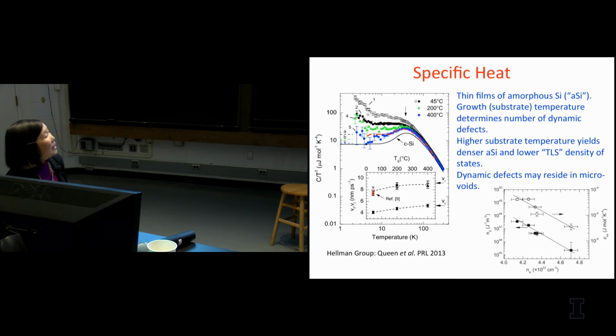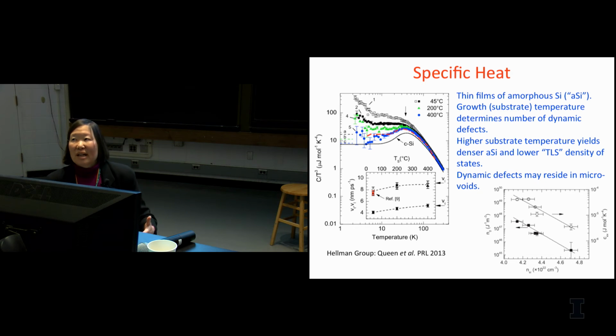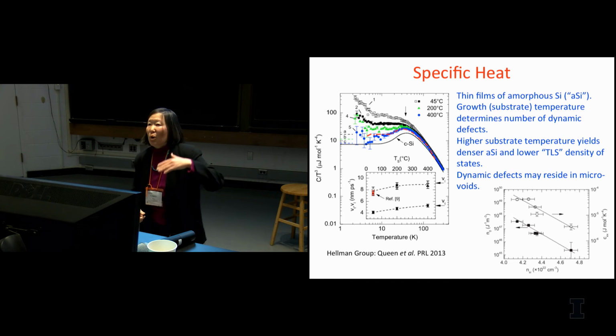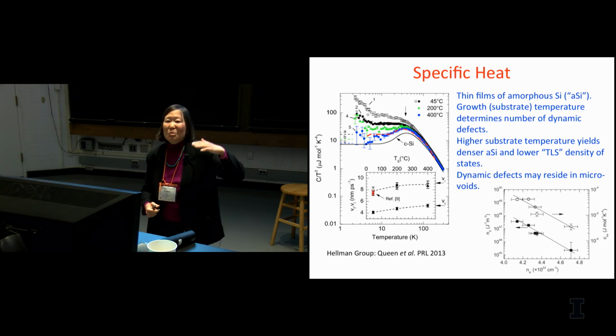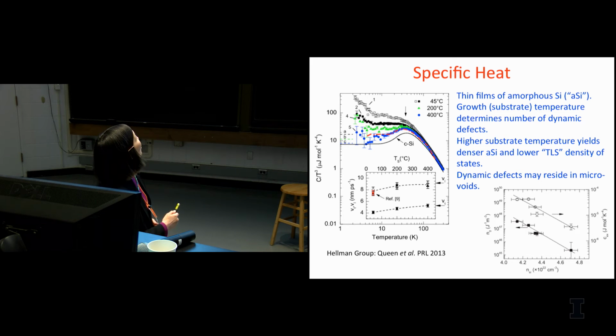Other measures of specific heat are in amorphous silicon thin films coming out of Frances Hellman's group at Berkeley. Here's C over T cubed versus temperature, and what they've done is change the growth temperature. They changed the temperature of the substrate, and when the substrate's very cold, like 45 Celsius, they see something similar to these low energy defects, but as they increase the growth temperature, at 400 degrees they get a great reduction. They find that the density of the silicon changes with the growth temperature.